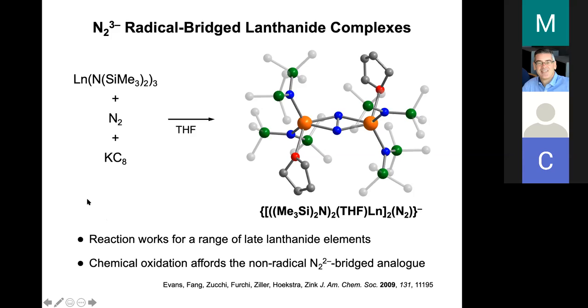But the way to engage lanthanides in a somewhat stronger exchange interaction is to use direct exchange, where the lanthanide's spin can have a Heisenberg exchange directly with the spin of a ligand. So if we have an unpaired electron on the ligand, that can have a strong interaction. And if that ligand bridges two or more lanthanide centers, then you can have a strongly coupled large moment for the ground state.